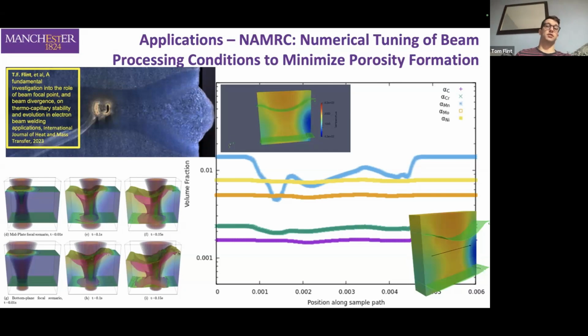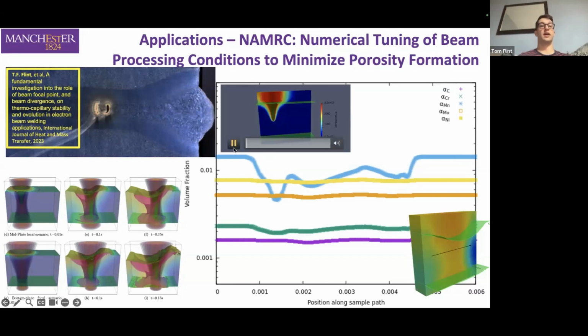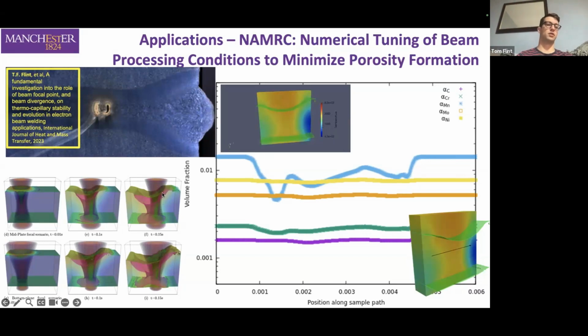So we did this numerical optimization campaign where we used this mathematical tool we developed, and we were able to go from a scenario where we had quite a lot of porosity in the weld to choosing the power ramp down parameters so that the keyhole collapsed very nicely. As you can see, there's no porosity in this weld. This is some examples of what we varied, and this is a paper you can read if you're interested. So, varying the electron beam parameters to mitigate against porosity, basically.